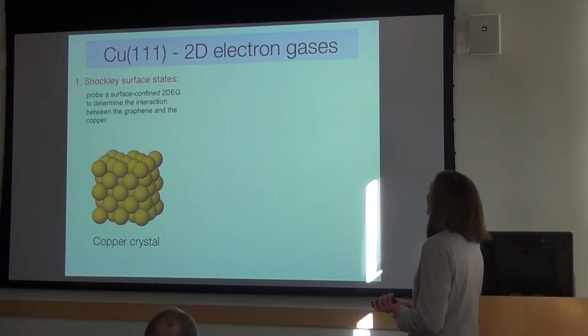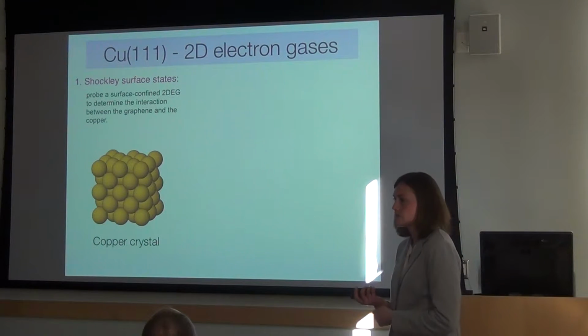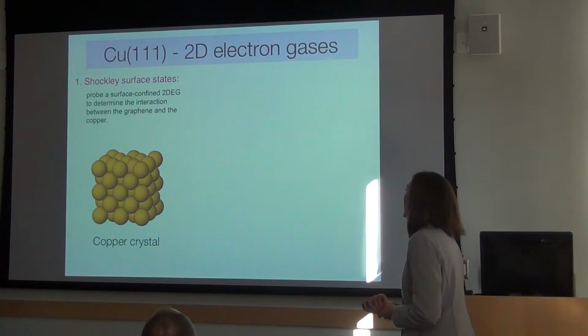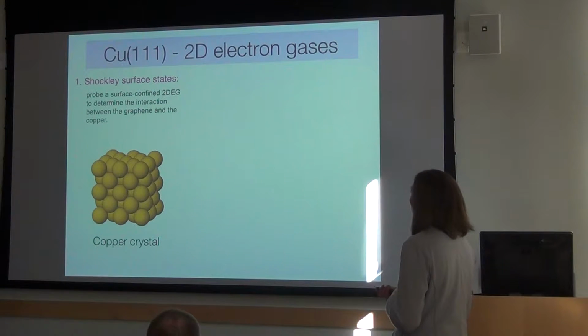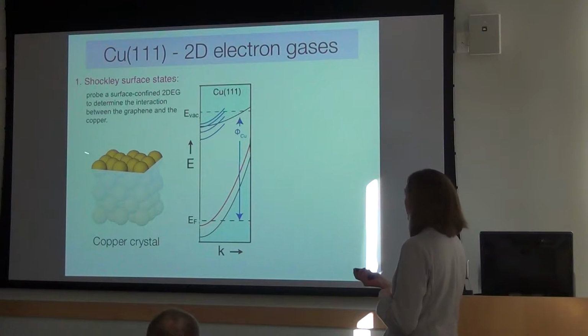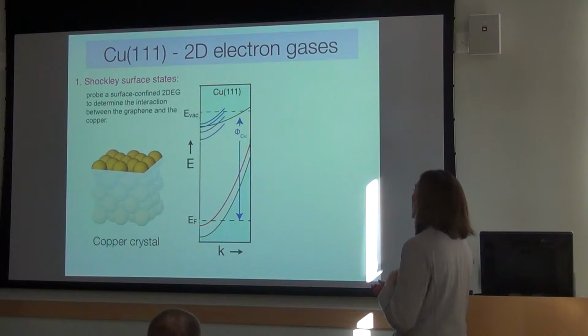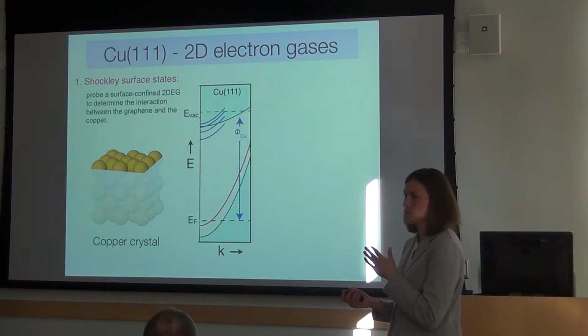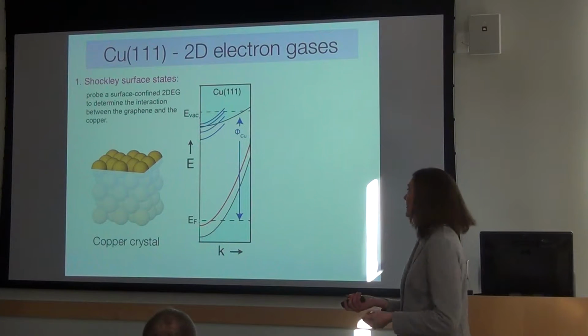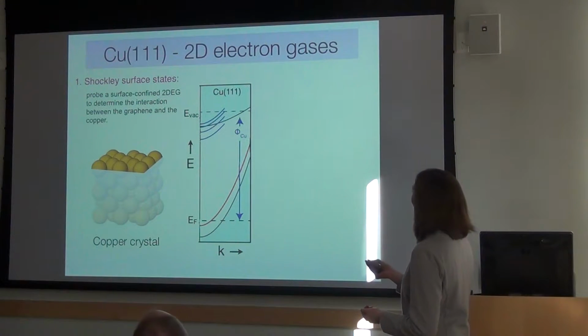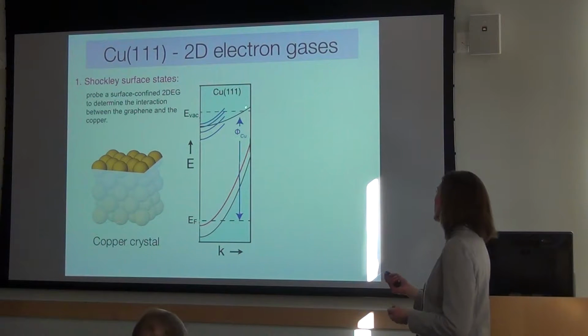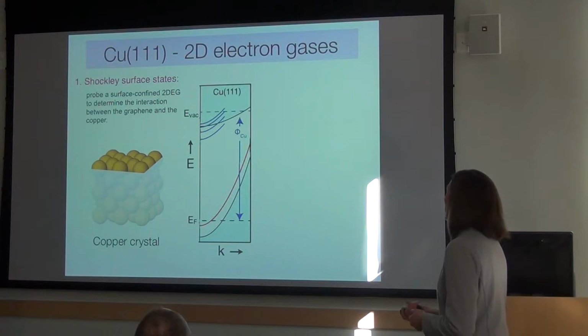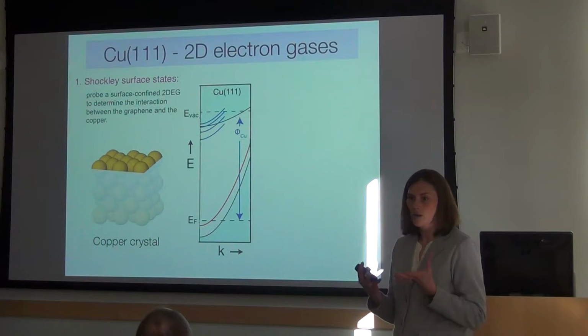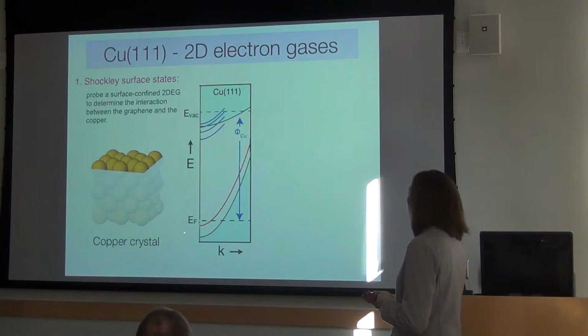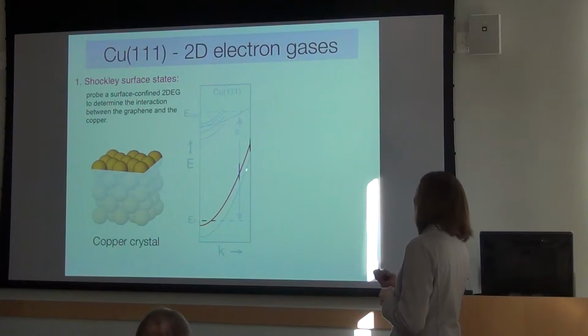Okay, so first we have to look at copper. This is the substrate that we're using. We're looking at this 1-1-1 surface of copper, which, when you cut the copper crystal off at a surface, can form what's called a surface state. This is the main structure I want to tell you about. The blue shaded regions are the electronic states of the bulk copper crystal. And then along the 1-1-1 surface, you have this red band here. This is a surface state.